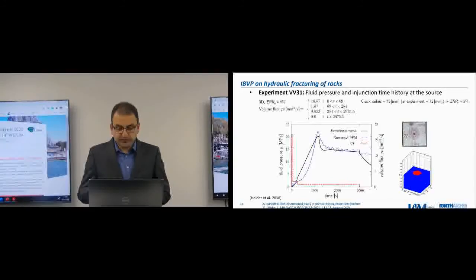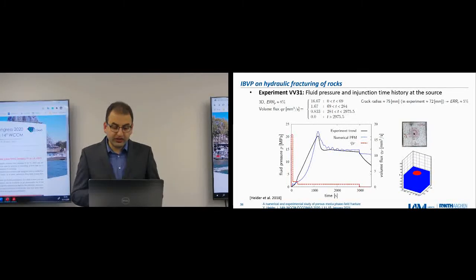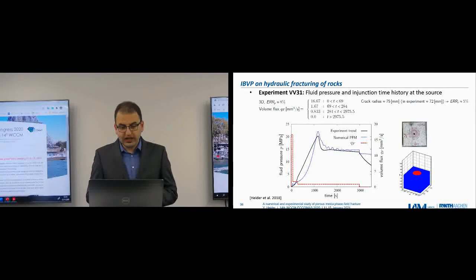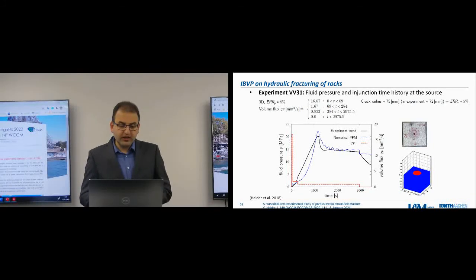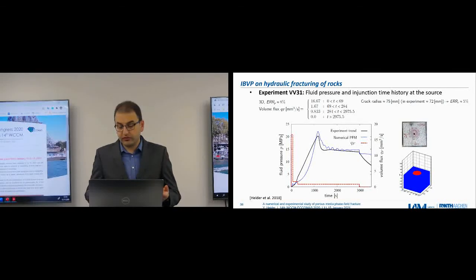You see the red line represents the fluid volume flux, and it's changing with time. We assigned exactly the same flux in our model. And then we are looking at the black and the blue curves, which represent the pressure time history. They have the same tendency, and if we look at the maximum pressure needed to initiate the crack, we see that our model can approximate this value with an error of almost 8%. Also, the crack radius is comparable with the experiment with an error of 5%.